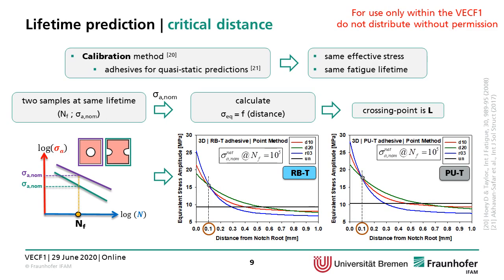So the idea is to take 2 samples at the same fatigue lifetime, as you can see here, 2 notches, one with internal notch, one with external notch. Although they have different nominal SN curves, by taking a point with the same fatigue lifetime and plotting the distribution of equivalent stress amplitude, the point where these curves cross is the point where theoretically they have the same effective stress. This crossing point is the critical distance. In this case, for both adhesives, the critical distance was 0.1 millimeter.